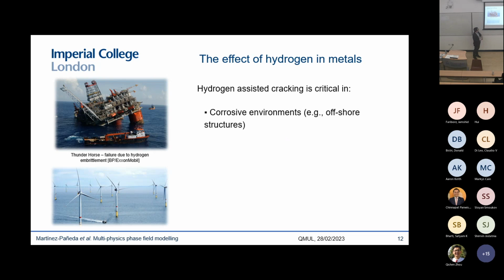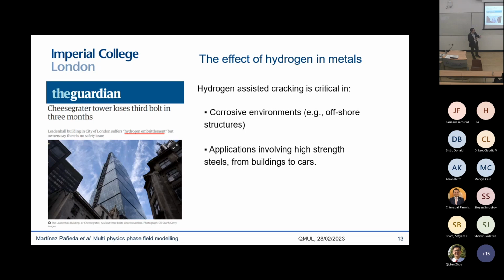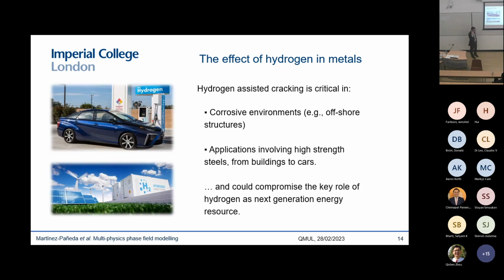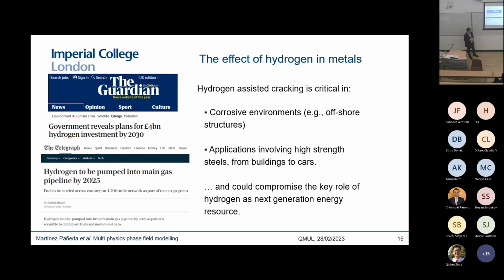So traditionally, hydrogen was a problem related to aggressive environments, such as those of offshore engineering. But now with the use of these modern steels, we're starting to see failures across all applications and sectors. So this is a newspaper article speaking about hydrogen-assisted failures in the Cheesegrater Tower, so not too far away from here. And you can see that it's just the hydrogen coming from the manufacturing or the exposure to humidity that is sufficient to trigger cracking problems in these more susceptible materials. And back to the first topic, right? How are we going to deploy this hydrogen energy infrastructure, given that hydrogen is changing so drastically the mechanical and fracture properties of metals? And it seems that politicians have already made a decision in that regard. It seems that they're going ahead with this hydrogen economy.